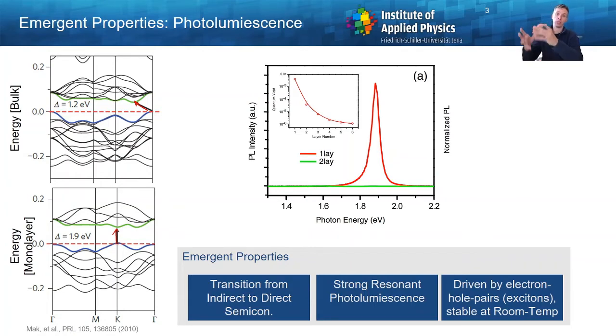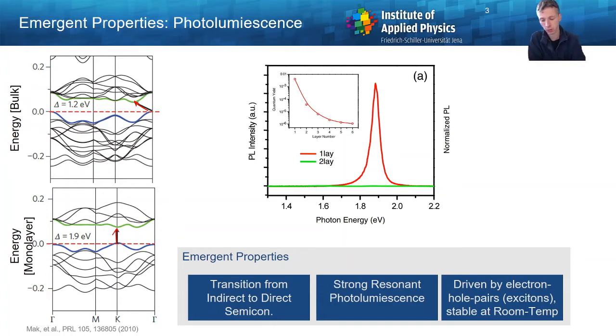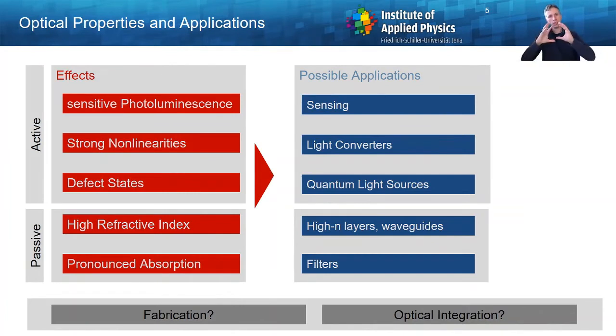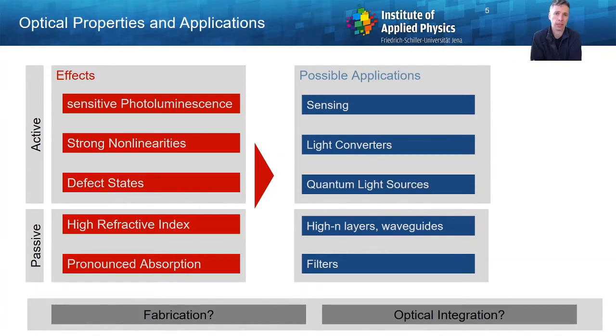This change from indirect to direct transition enhances light-matter interaction effects rather drastically, as you can see for example from a photoluminescence spectrum. If you excite your material with short wavelength light and you have a monolayer crystal, you observe a very strong photoluminescence in the red at 670 nanometers, as opposed to a two-layer crystal where this photoluminescence is very negligible. This photoluminescence is driven by electron-hole pairs which are frequently called excitons. Each of these effects could lend themselves very nicely for applications in optics and photonics.